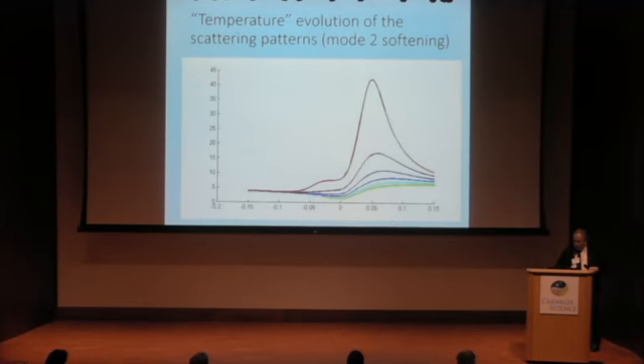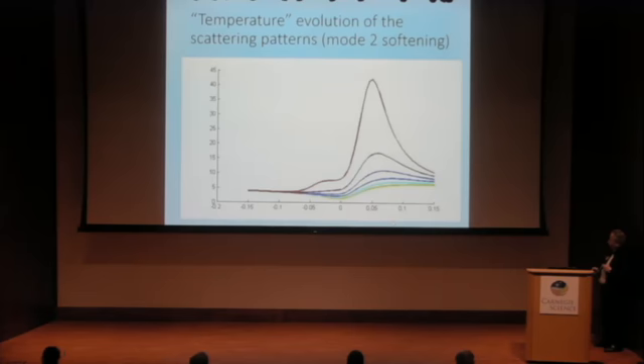Now let's have a look at how the temperature evolution of the diffuse scattering integrated over energy should look. It starts from a very weak peak on one side and a minimum on the other side, and at some moment we have a situation very similar to what we observed and to what was described by Marek and Irka. So that's more or less a possible description.